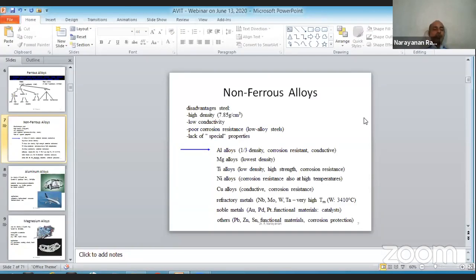High density means per unit volume, they weigh more. But what happens is the patient should carry heavy weight for a small volume. He's already having a body weight of, say, 60-something kgs. And if a small portion, say elbow or hip or knee, is placed with a heavy metal like stainless steel, then he will feel excruciating pain. So that is one major disadvantage of stainless steel. Secondly, stainless steel is composed of nickel, and as I told you, it is always placed inside the highly corrosive body fluid. So in such a case, what will happen? The nickel of a stainless steel comes out, it dissolves out. And if nickel comes out of the stainless steel system, stainless steel loses its integrity. And the leached out nickel travels throughout the body stream and can be carcinogenic. This is the problem with stainless steel.